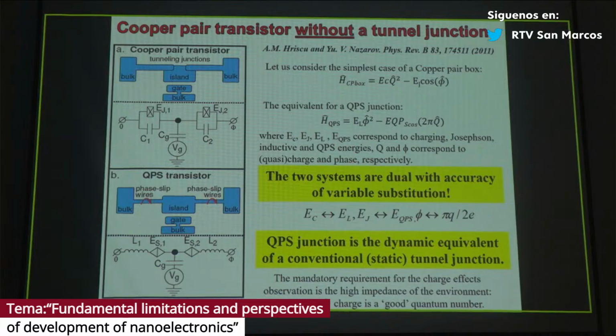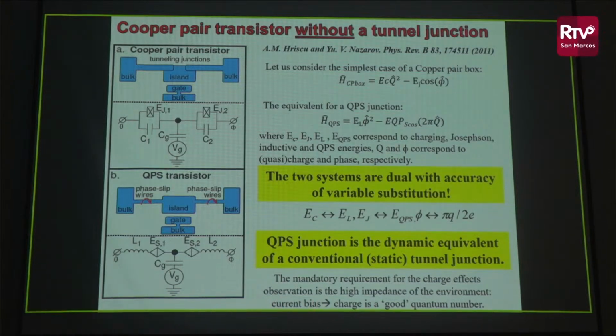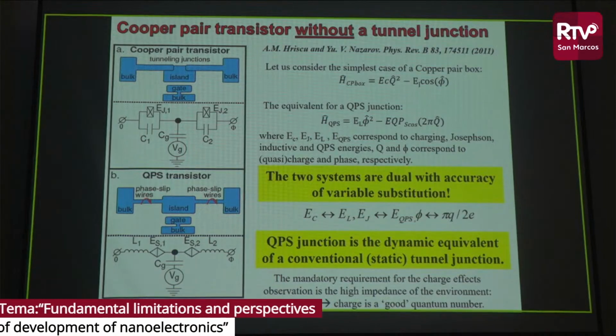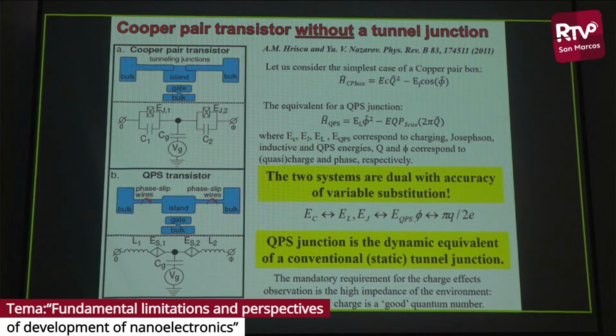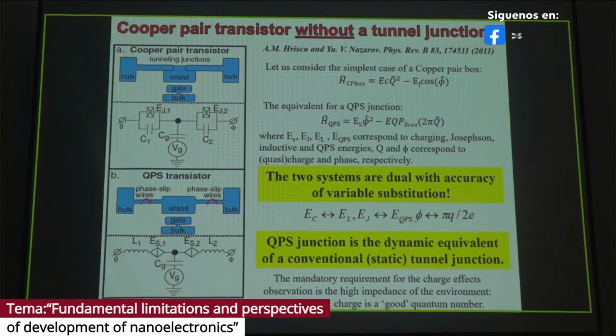So all the physics which is observed in single electron devices, superconducting devices, can be observed in a device where there are no tunnel barriers, but instead there are very tiny nanowires. The only problem is that you should fabricate such a structure where the two conjugated parameters, charge and superconducting phase, are conjugated. So if you want to obtain the regime of very strong fluctuations of the phase, you should stabilize the current. And stabilizing the current is not just a good Keithley current source, it is to put high resistive or high impedance balancing devices very close to your nanostructure.